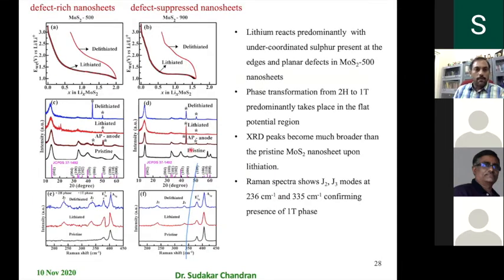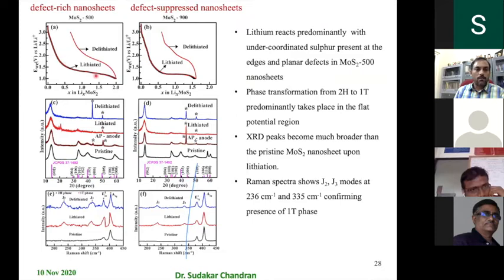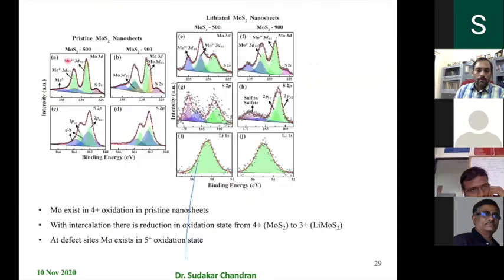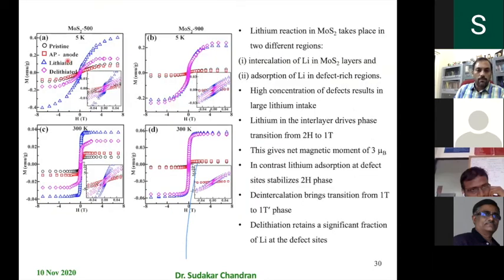So, of course, here we show how much lithium can get into the molybdenum disulfide. For example, when you have defect-rich molybdenum disulfide nanosheets, you can see typically 1 lithium is what it can take. For example, sorry, where did I go?